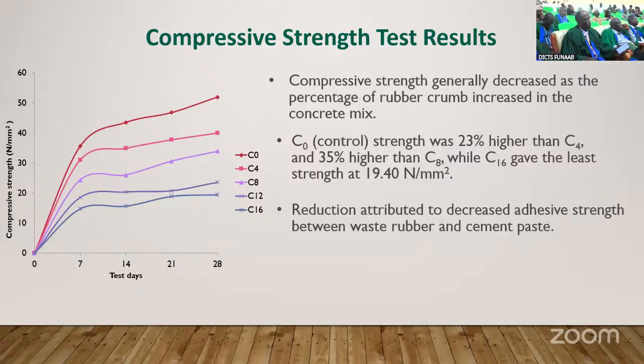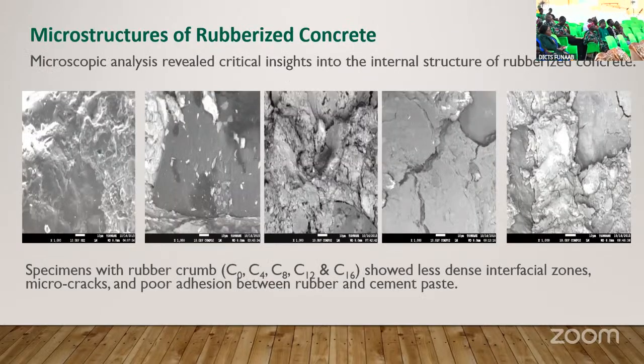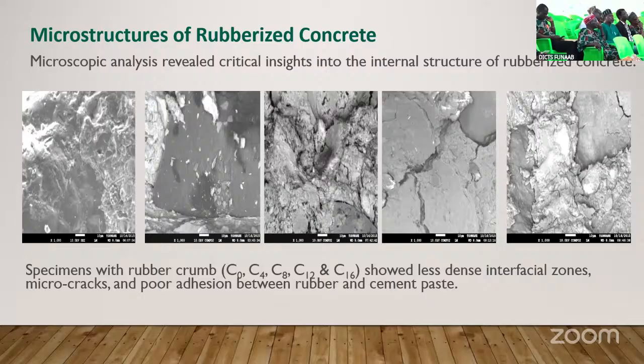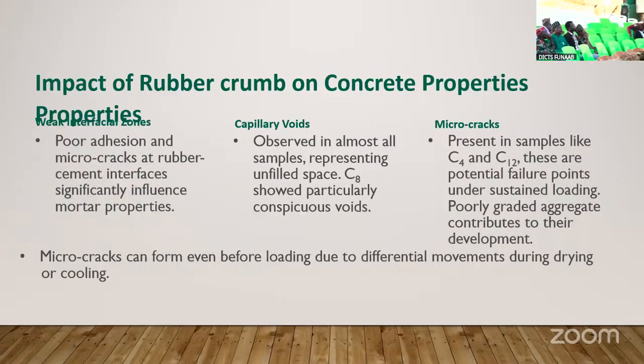The compressive strength generally decreased as the percentage of rubber crumb increased in the concrete mix. The control strength was 23% higher than the C4 and 35% higher than the C8, while C16 gave the least value, 19.40. The reduction is attributed to a decrease in adhesive strength between waste rubber and cement. You see that the strength was reducing as more rubber crumb was being added to it. Some would think that is an advantage, but wait to see what is happening. The microstructure was studied. Specimens with rubber crumb showed less dense interfacial zones, micro cracks, and poor adhesion between rubber crumb and cement. Now, the impact of rubber crumb: poor adhesion, a lot of capillary voids, micro cracks, and so on and so forth.